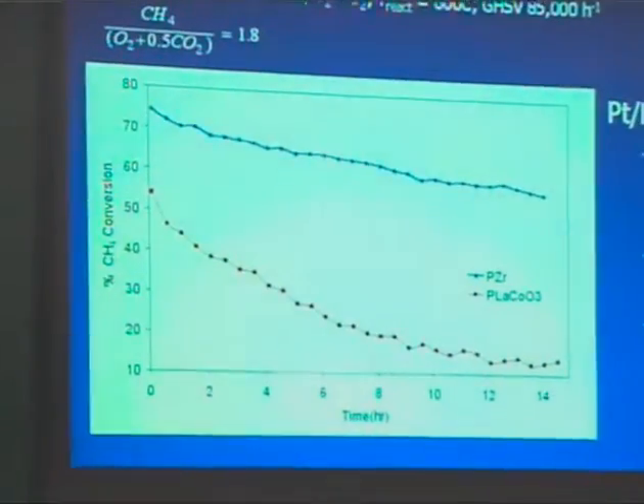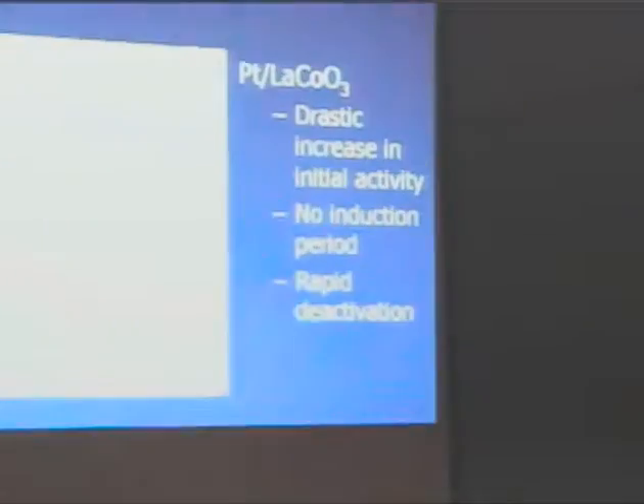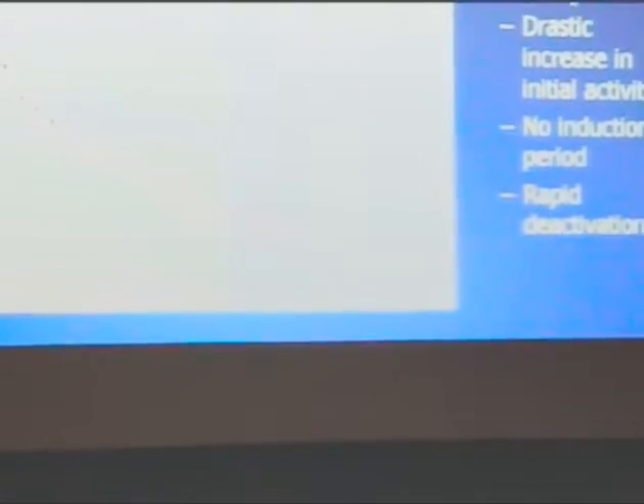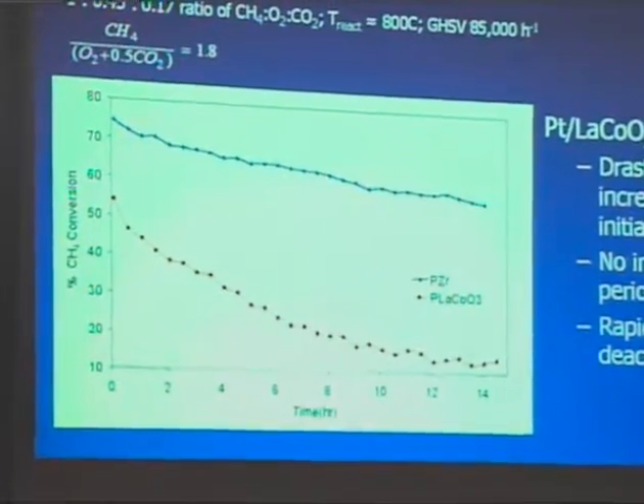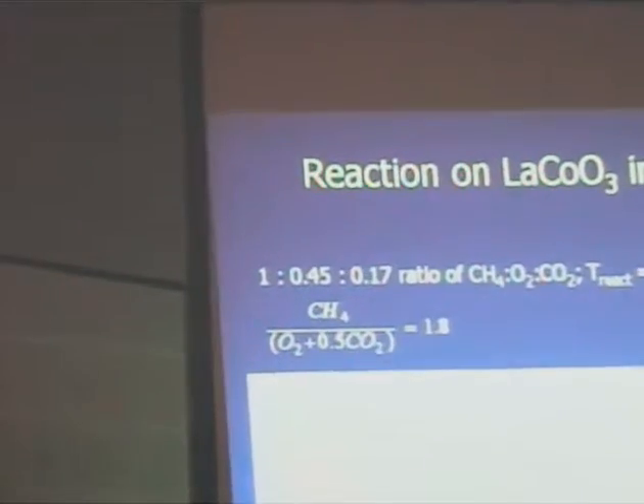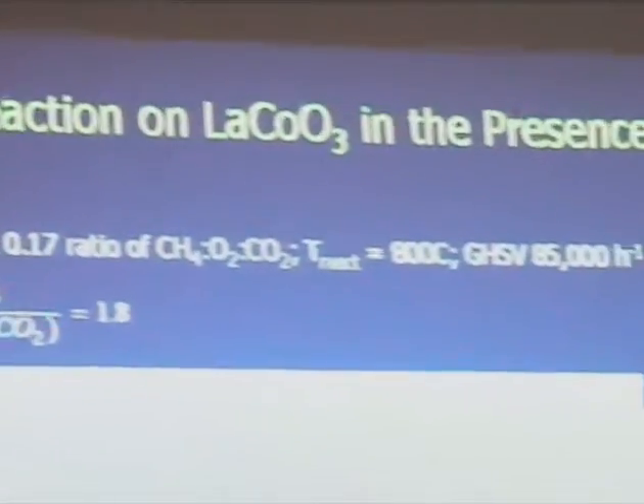When we looked at the perovskite now in the presence of oxygen, and we pretty much abandoned the strontium iron cobalt, so you won't see that appearing anywhere else. When we've done the presence of oxygen on the perovskite material, we see a dramatic increase in the initial activity, and that most likely is due to oxygen that is aiding in the uncovering of the platinum, as well as oxygen converting methane, with a high amount of oxygen, having a reaction to CO2 and water. We see a rapid decrease in the activity, rapid deactivation, again due to carbon formation on the material.